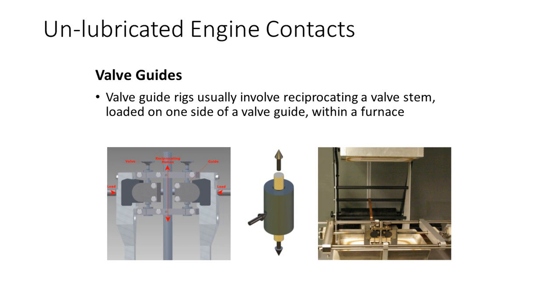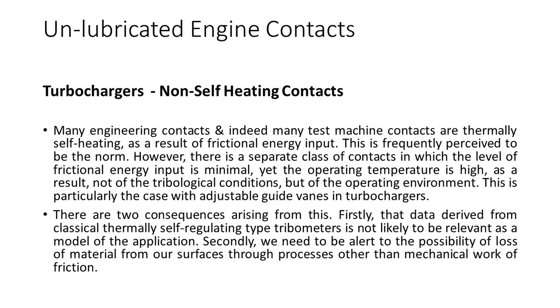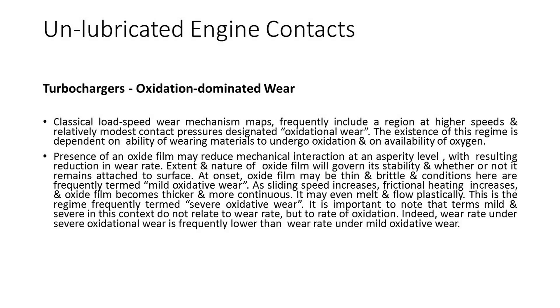Valve guide rigs usually involve reciprocating a valve stem loaded on one side of a standard valve guide within a furnace. Many engineering contacts — and indeed many test machine contacts — are thermally self-heating as a result of frictional energy input. However, there is a separate class of contacts in which the level of frictional energy input is minimal, yet the operating temperature is high — not as a result of the tribological conditions, but of the operating environment. This is particularly the case with the adjustable guide vanes in turbochargers. Data derived from classical thermally self-regulating tribometers is not likely to be relevant as a model of this application.